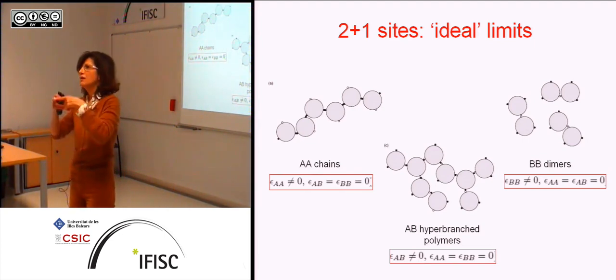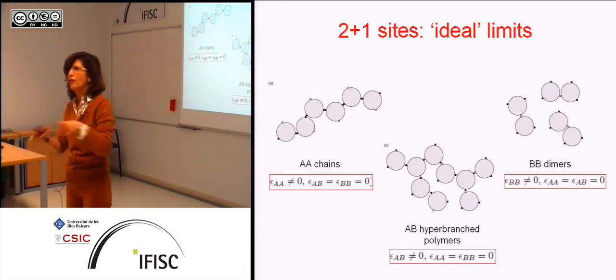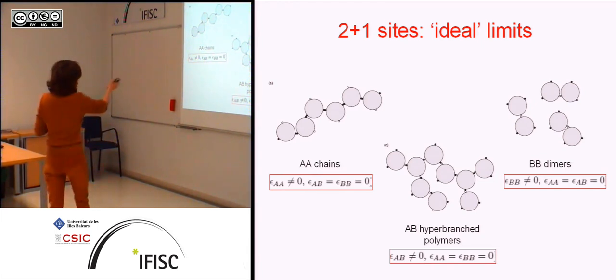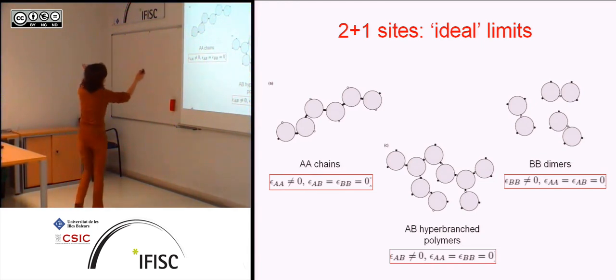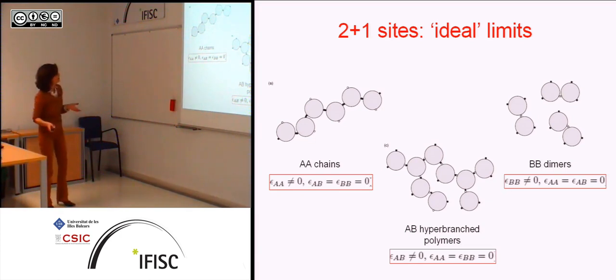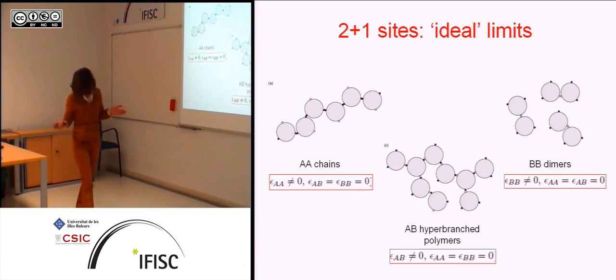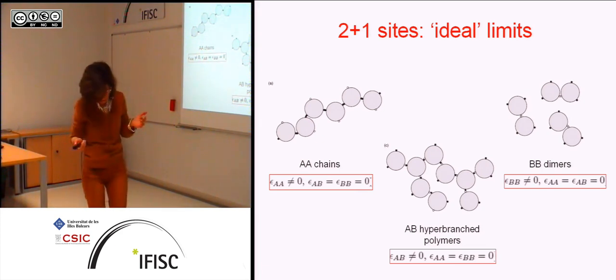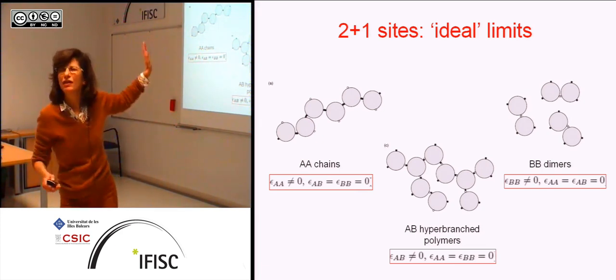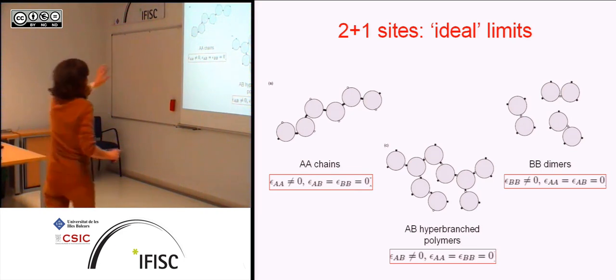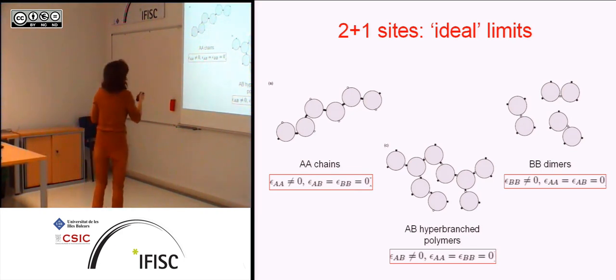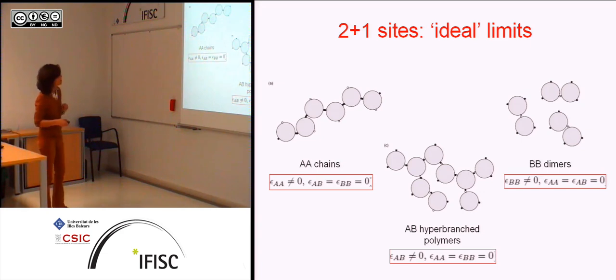Ideal meaning that they do not condense. They don't have two-phase separation. Linear chains can form, but if you switch off the BB interactions and the AB interactions, and only leave the A interactions, these chains do not condense. If they're very rigid, you could have some nematic transition, but these are Gaussian chains, so these won't even form a nematic phase in the model anyway.